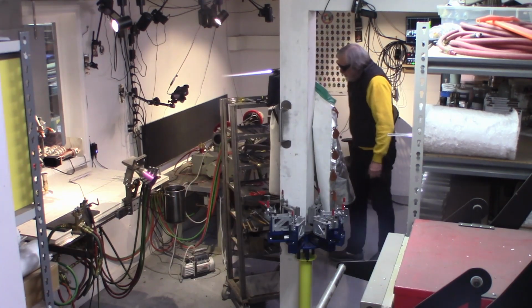I preheat the plate and the components to 1500 degrees F, which is right below the softening point of boro. I went through a lot of experiments trying to figure out how hot to preheat it, because I'm fighting a battle here, staying right on the edge of getting hot enough for the glass to fuse, but not so hot that it sticks. And when glass sticks to ceramic, it sticks really good. I think that's why they call it glazing in pottery making. It actually fuses together, and once it sticks, it's impossible to fix. So we're at 1500 degrees.